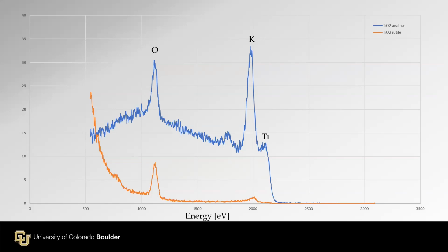And I prepared those powder reference samples and performed atomic oxygen cleaning to remove surface hydrocarbon contamination. After 10-20 minutes of atomic oxygen cleaning, I collected those spectra. Okay.